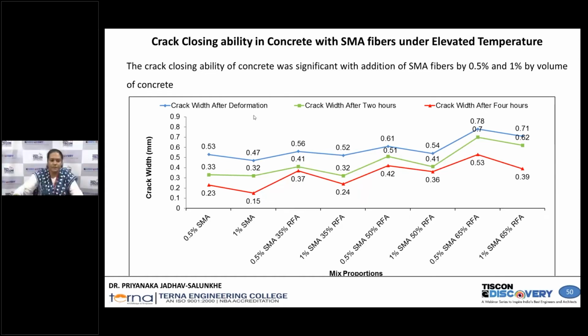Here also we measured the crack width in the cylinders after testing. We observed that immediately after testing the crack width is 0.47 mm. After 2 hours of testing it got reduced to 0.32 mm, and after 4 hours of testing it got reduced to 0.15 mm. So this is a drastic change in the recentering capacity of the FeSMA reinforced fibers.